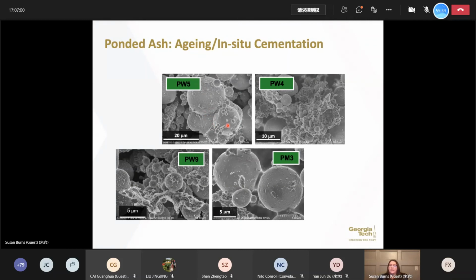So we have surface texture. You can see those particularly pronounced here in the lower left-hand corner. But we also have evidence of in situ cementation. What you see at the interface of these 2 cenospheres is a mineral interface that has been left behind as the meniscus between those 2 particles has dried, and the salts, or in this case, I think this was calcium sulfate, if I remember correctly, have precipitated here in the form of the meniscus. So we do have some in situ cementation, which is occurring when we have these ashes disposed in this way.